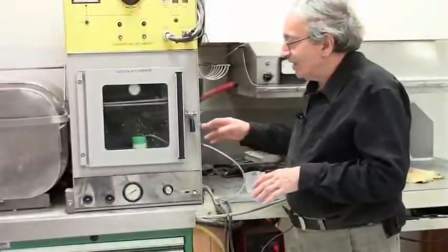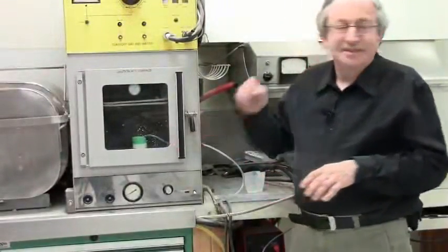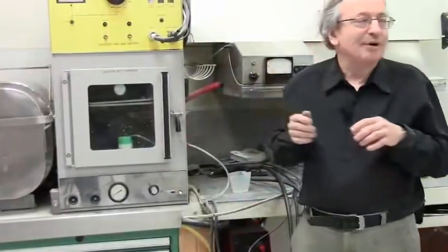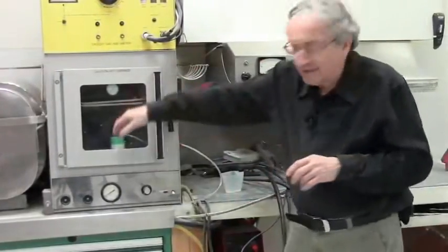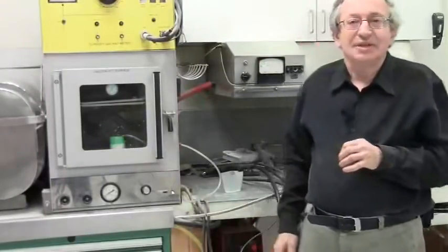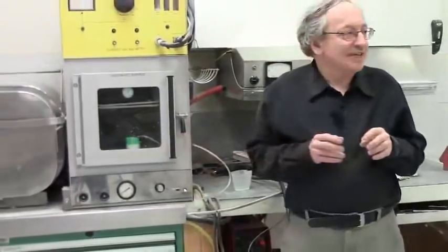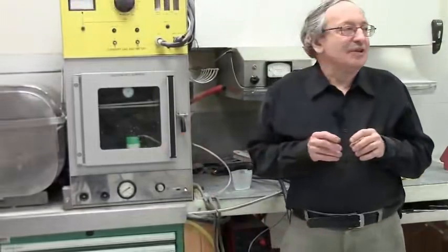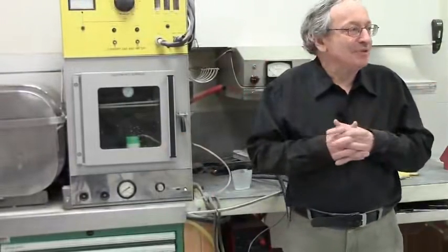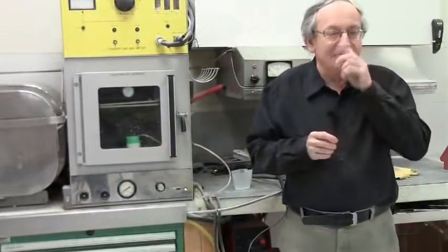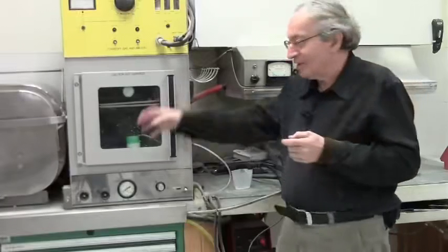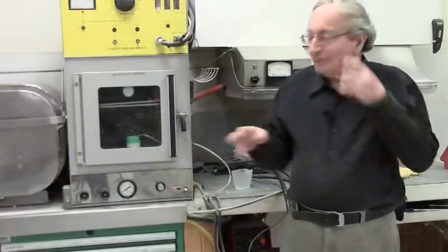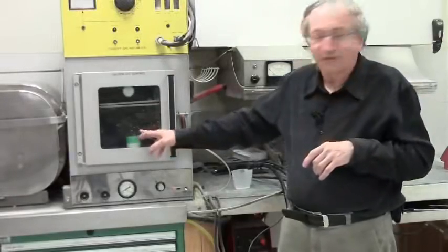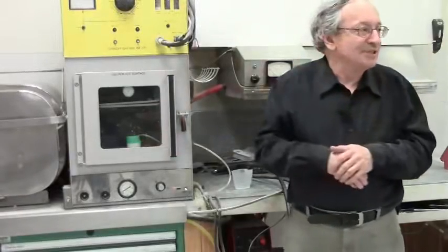Now once you release the vacuum, two good things happen, okay? Even if the material is degassed, some miniature air bubbles were introduced by sucking it in and putting it in. Now these air bubbles may have been trapped still inside, but once you release the vacuum, these bubbles collapse because these bubbles inside have very little air because it was all done under vacuum. So even if there were bubbles introduced and what you saw at the end, the foam which was formed, it will all collapse and disappear.